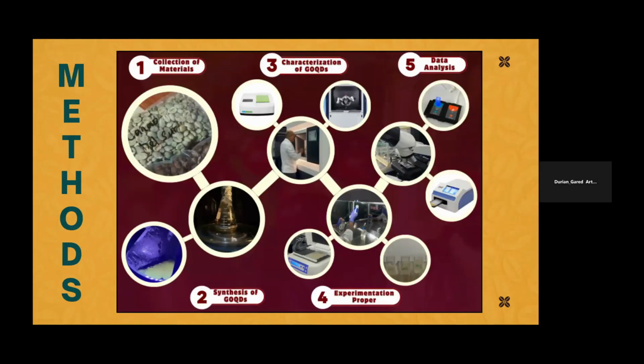The synthesis process is as follows. The Coffea arabica beans were separated from their contents and thoroughly washed in distilled water for 5 to 10 minutes to ensure cleanliness. The beans were then air dried for 24 hours. Following this, the beans underwent a typical coffee roasting process wherein black carbon was formed. Finally, the black carbon from Coffea arabica beans was blended until it reached a fine powder consistency, preparing it for the extraction of GOQDs.